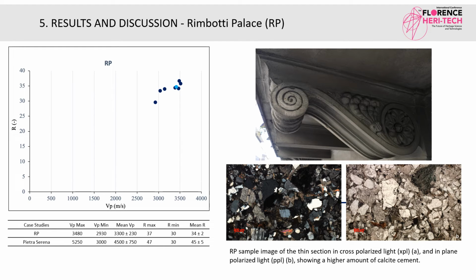The values of Vp and R of Rimbotti Palace corbels indicate a good level of compactness and adhesion of stone materials. The maximum values of the two measures correspond to the corbel with the lowest level of degradation, while the minimum to the corbel with higher decay. The mineropetrographic observation shows little presence of clay matrix, a higher amount of microsparitic calcite cement, and a consequent higher compactness. The clastic granules are of homogeneous size, mainly constituted by the same components. The lithotype of RP samples is characterized by higher Vp and R values. In fact, in thin section, it has lower macroporosity and a higher content of calcite cement than the previous sample.